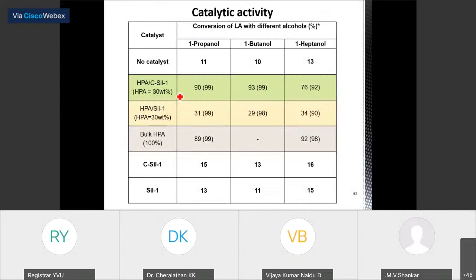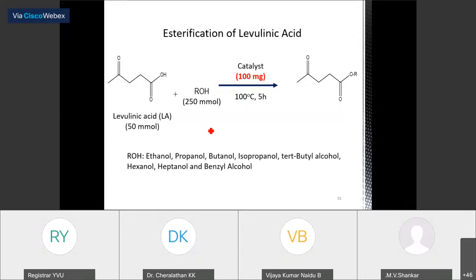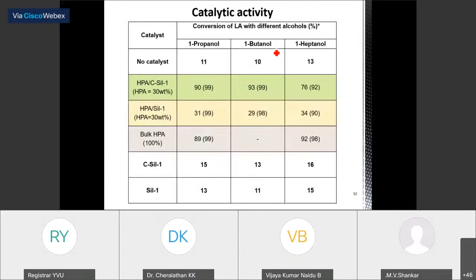Then we performed a reaction. It's nothing but esterification of levulinic acid in the presence of bulky long chain alcohols: propanol, butanol, heptanol. All these alcohols were used to esterify. The esterification is an acid catalyzed reaction, and this zeolite is performing this well. If you look at this, the 30% HPA loaded catalyst is showing almost equal activity compared to that of bulk HPA. This 100% HPA is only 30% HPA loaded on this zeolite. So that is where this difference comes in.